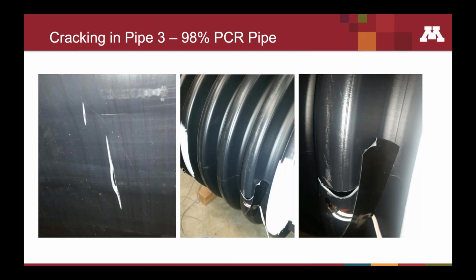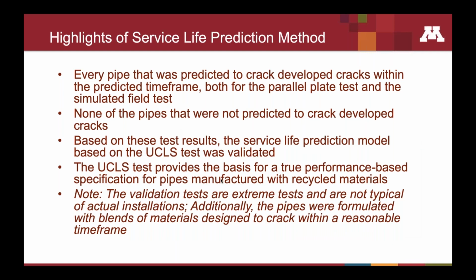And this image shows one pipe with 98% post-consumer recycled material that generated cracks, and that crack happened to occur within days of when we had predicted it to occur. So we felt that the model was justified, and incidentally, I've spent about 20 years of my career working in the plastic pipe industry, and I can say that this is the only time in my 20 years that I was actually happy to see a pipe that cracked, because it really validated our model, and we would have had to start over basically from new if we were not able to validate this model. So that was a very exciting part of our research.